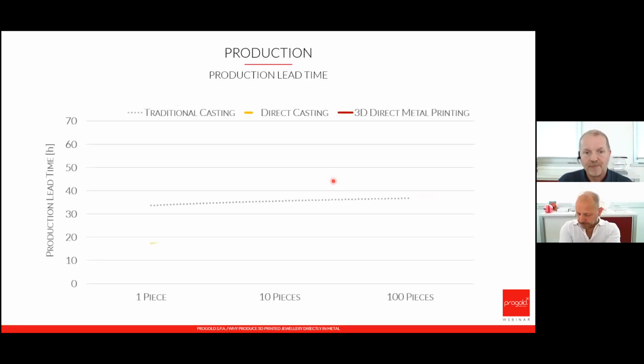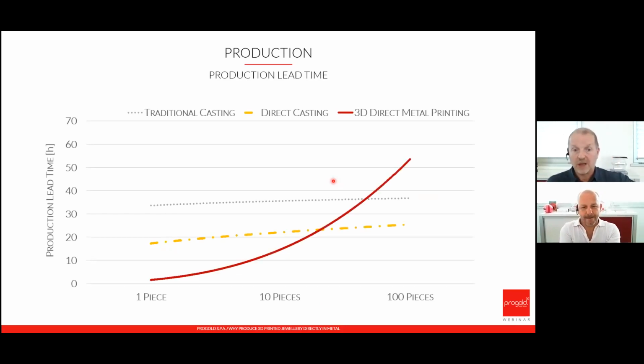Production lead time. The chart shows how SLM lowers production lead time compared to casting for prototypes, one-offs, and small batches. You see that the production lead time is lower for SLM. And I spoke of small batches: it depends for sure on geometries and on the weight of the parts, but basically up to small quantities, that is 15 pieces, 20 pieces, something like that, SLM maintains this kind of advantage compared with traditional casting and direct casting.